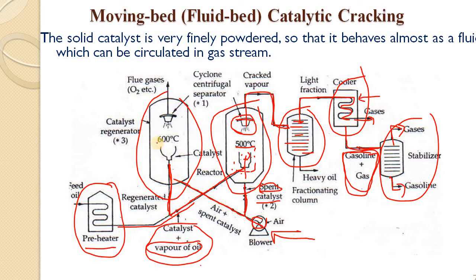The catalytic regenerator is maintained at 600 degrees centigrade. At this temperature, the carbon particles are separated from the catalyst — the unburnt carbon particles are removed as flue gases by a cyclone centrifugal separator. The fresh, regenerated catalyst — zeolite, that is aluminum silicate (SiO2 and Al2O3) — is allowed to pass through a pipe to mix with the incoming batch of fresh vapor oil, and the process is repeated to convert cracked vapors into gasoline and gas mixture.